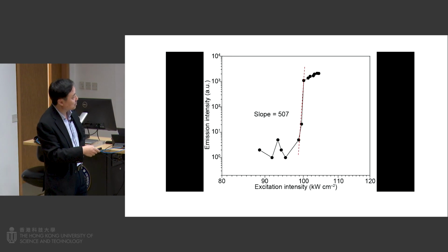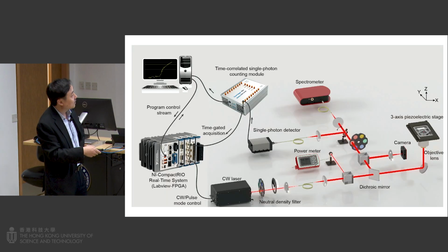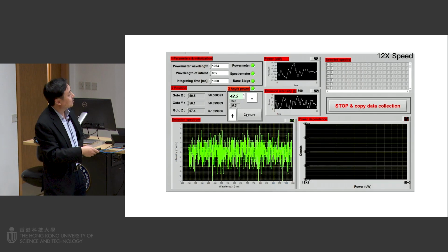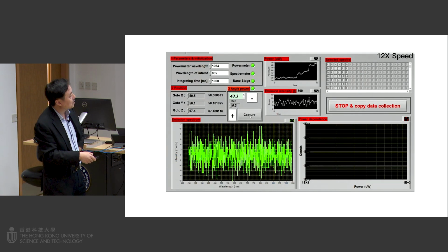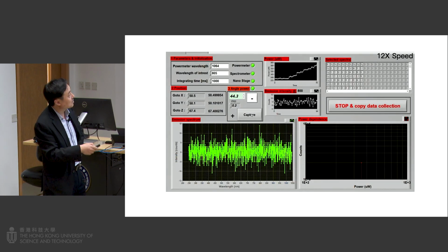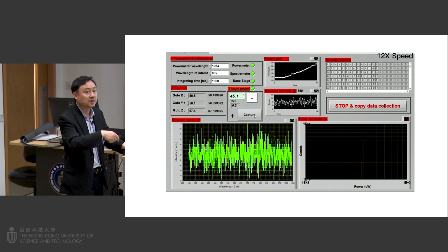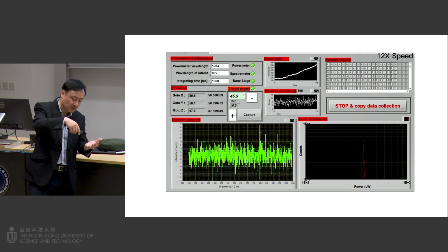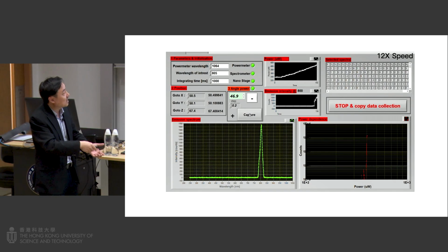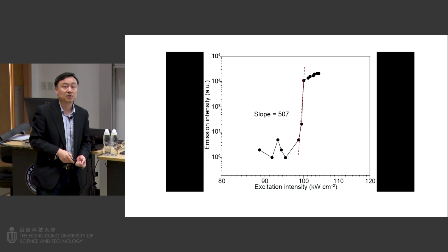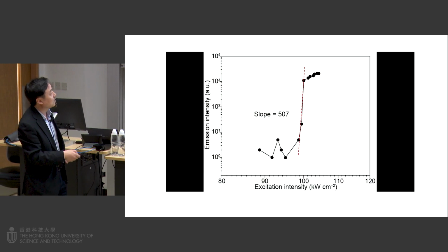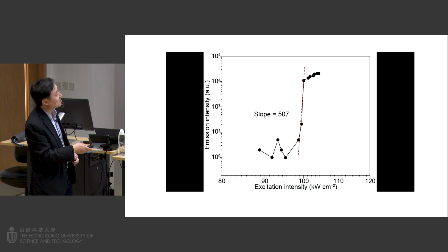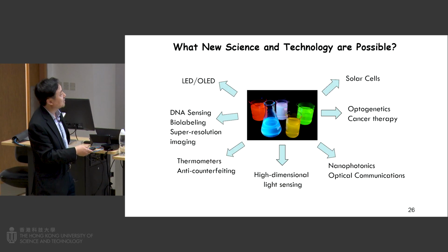let me show you again here. We measure the 800 nanometer emission. So we keep increasing. The material is a magical material. You keep increasing the excitation intensity, then suddenly you see a huge emission output. So you measure the slope. The nonlinearity factor is around 500.